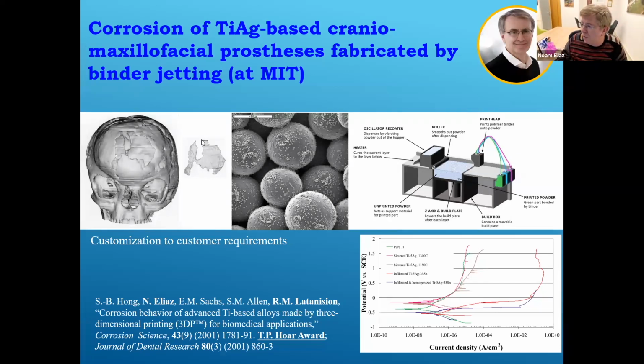So what you can see on the left-hand side is a 13-year-old boy from the Boston area that was born with this defect. On the right-hand side, you can see the computer reconstruction of the defects that you can see, using a CAD file. Typically, these kinds of defects are filled by using casting. But as you know, titanium is difficult to cast.